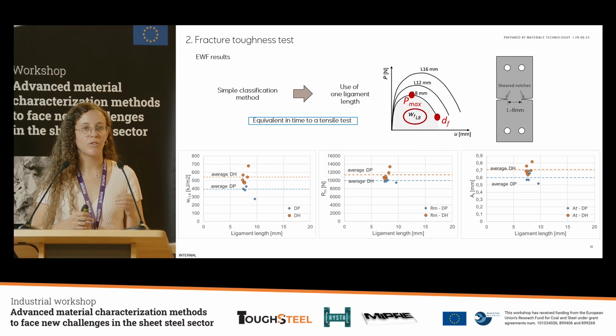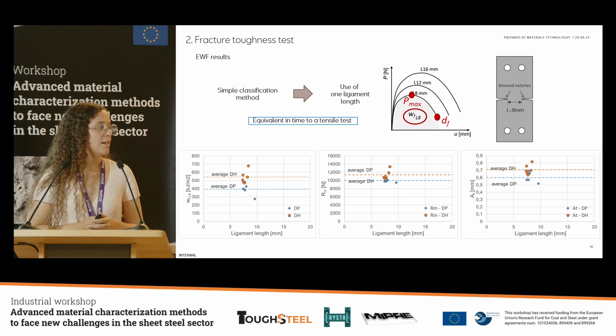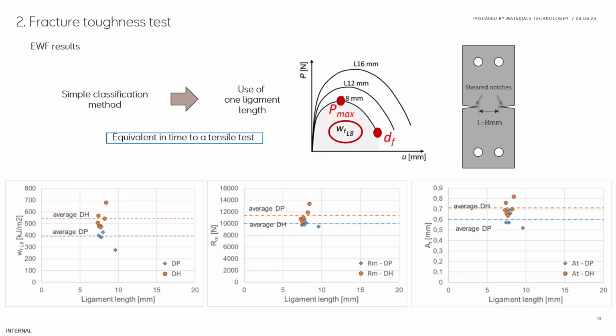One was the work of fracture, which is this area under the load displacement curves. We also checked the maximum load of these curves and the displacement at fracture. And we could see in the results that the materials were scaling similarly to what we found with the complete essential work of fracture method. So this could be a new step that we could implement with the essential work of fracture and how to predict edge cracking or fracture-related problems.